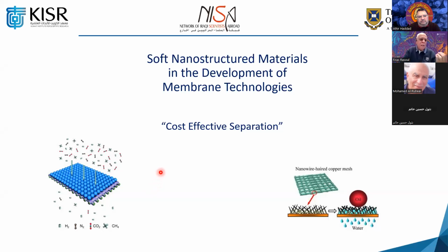So what happens is that from the seawater and from all the biological compounds and macromolecules, they start to foul, causing blockage of the porous structure on the membrane, and it is reducing the efficiency of these membranes. Even though we did not do much active work on that, we are planning to do this.